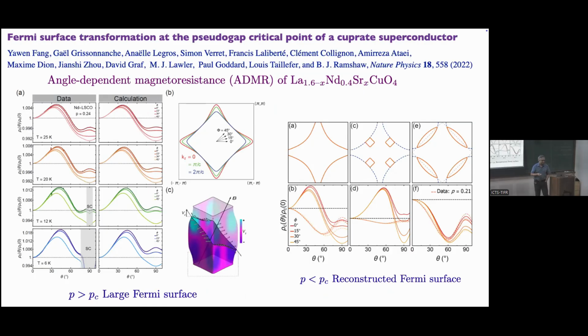But on the other hand, in recent experiments, the last 2 or 3 years, a totally different picture seems to be appearing from magnetotransport. So what you'd like to see are the famous quantum oscillations, because that's the foolproof measure of a Fermi surface. But nobody's seen that, presumably because the experiments are really difficult. The fields needed are very high. What they have seen is a precursor to quantum oscillation, which is called angle-dependent magnetoresistance. So here you take a magnetic field and you put it at some angle to the plane.